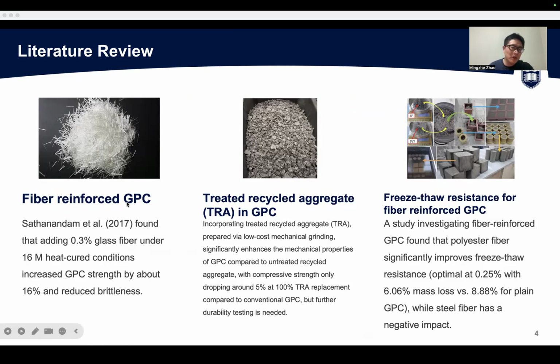There are studies that already investigated fiber reinforced GPC and found that fiber reinforcement can improve the mechanical strength of the GPC. Also, there are studies that investigated treated recycled aggregate in GPC and found that with 100% TRA replacement, the compressive strength only dropped around 5%. And coming to the freeze and thaw resistance of fiber reinforced GPC, a study found that polyester fiber significantly improves the freeze and thaw resistance, while steel fiber has a negative impact.